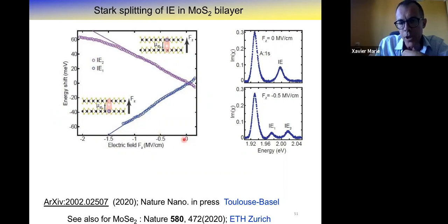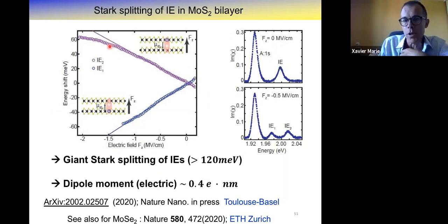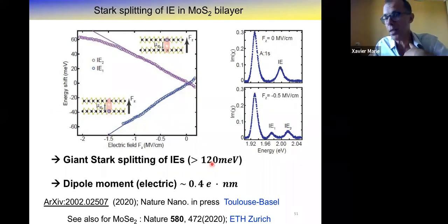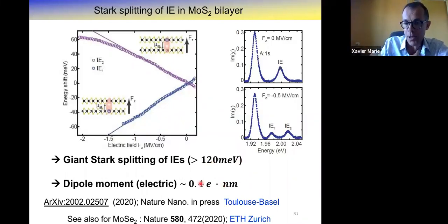And you see in moderate electric field, we have a rather linear shift, and the maximum is of the order of 120 millielectron volts. So it's a strong effect. And we have a significant dipole moment we can easily quantify with this kind of experiment.